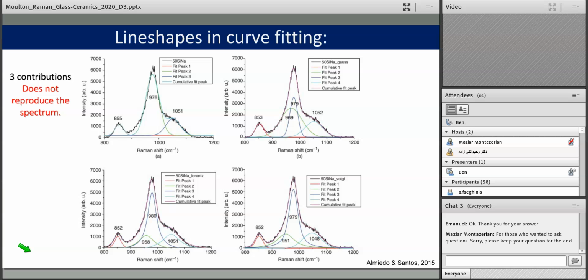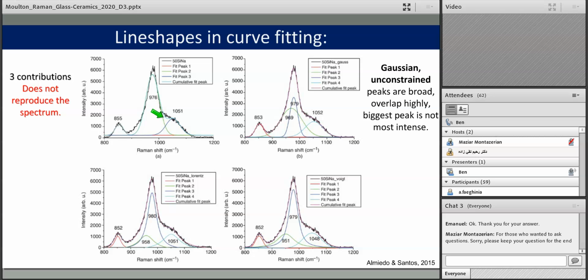Some examples of this. This is the same spectrum fit in 4 different ways, again from Professor Almeida. On the top left is a situation where 3 Gaussian bands are fit. And you can see they hit the peak at the top, and they get the shoulder on the high frequency side. But you can see that there are some gaps here. The center of the peak is not very aligned. There's another gap here. And so we would consider this quite a bad fit, and certainly you should not consider making an interpretation on that.